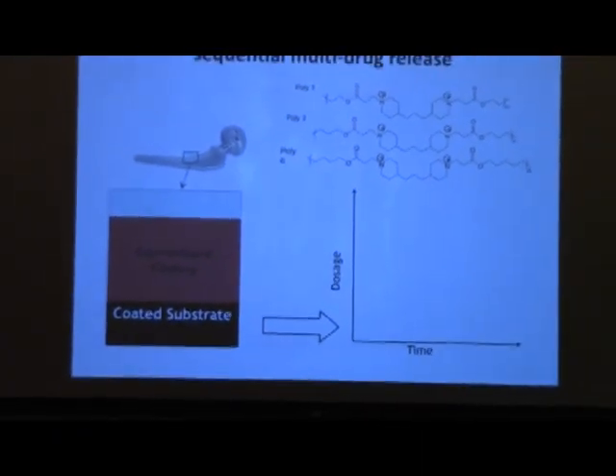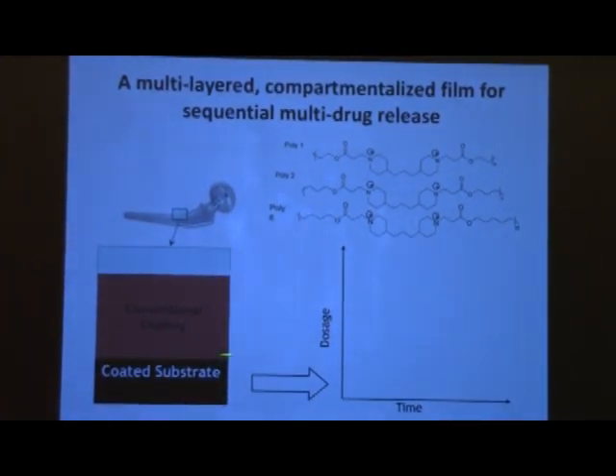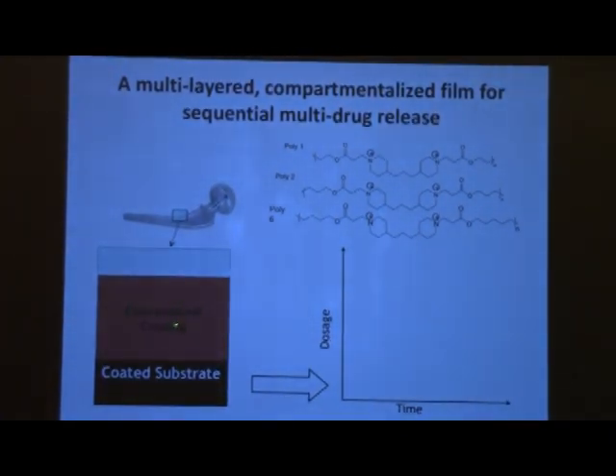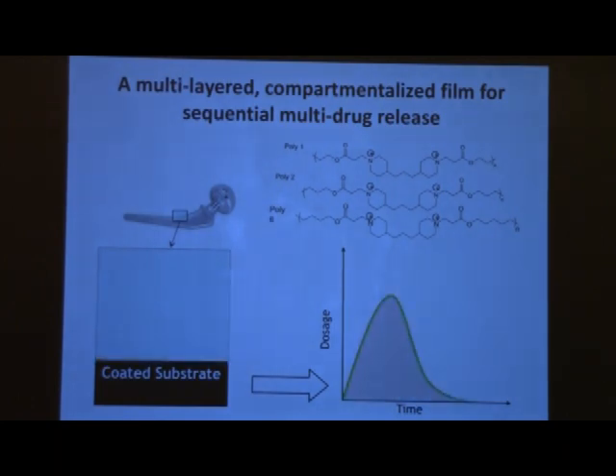So you end up only being able to put about 1 to 2 weight% of drug in before you phase separate. And if you phase separate, when you release the drug, it releases in a very rapid and short time frame. You don't get control. So you tend to use these materials to release small molecule drugs that are hydrophobic and will not be needed in large quantity. The other problem with a conventional coating is that if you put multiple things into that conventional coating, they all come out at the same time.